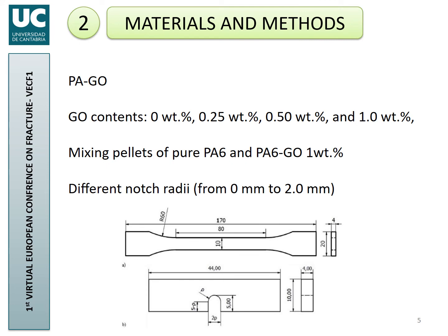So these are the materials that we analyzed. Polyamide 6 with graphene oxide, with graphene oxide contents of 0 weight percentage, 0.25, 0.50, and 1 weight percentage. The pure polyamide, the pure PA6, and the 1% graphene oxide content materials were provided by a producer in pellets. Obviously, 0 weight percentage material has no nanoparticles, and 1 weight percentage